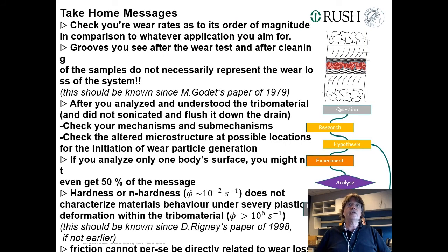What is the take-home message? Check your wear rates in your tribometers in order to the magnitude that you would like to have a comparison for whatever application you aim for. That's quite important. You don't have to run a wear test for 30 years, for instance, in energy engineering, because they ask for 30 years lifetime, but you can run a very small wear rate and then analyze the surface. And maybe if you're lucky, compared to something which lasted for 30 years, if you get hand of these parts,